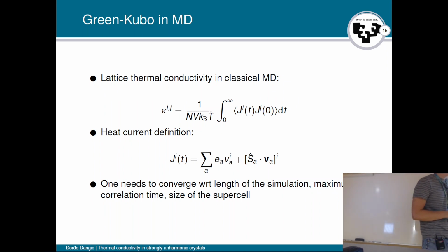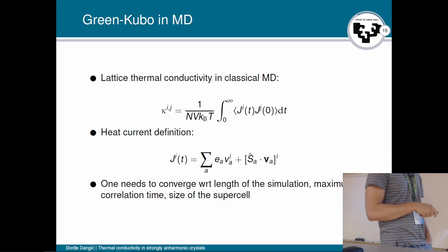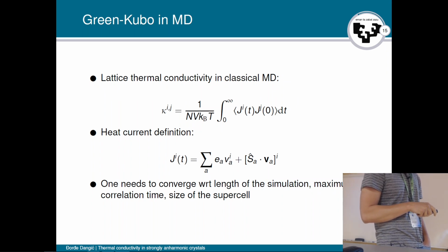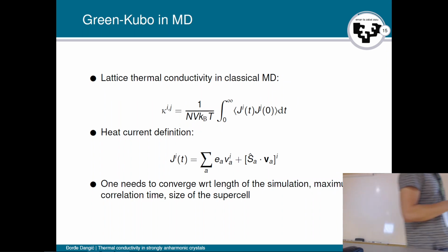There is an interesting thing here. This E_A is the local energy, so the energy associated with atom A. And immediately you can see that there is a problem if we are trying to run DFT, because DFT does not have a unique way of assigning energy to a particular atom. So for a long time, ab initio calculations of the lattice thermal conductivity using Green-Kubo and MD were not possible, but recently it has been proven that there is a gauge invariance that allows you to use Green-Kubo and MD.